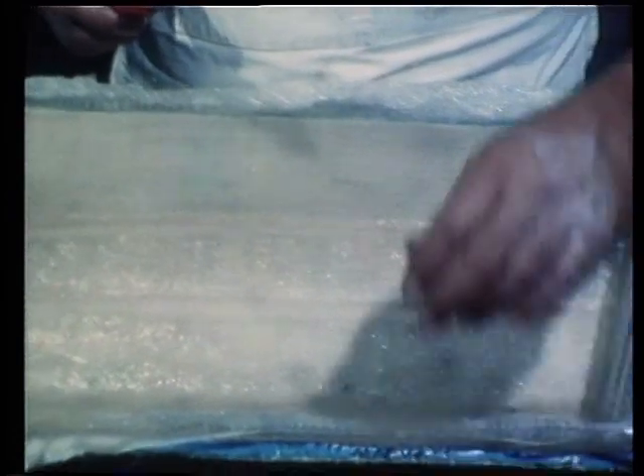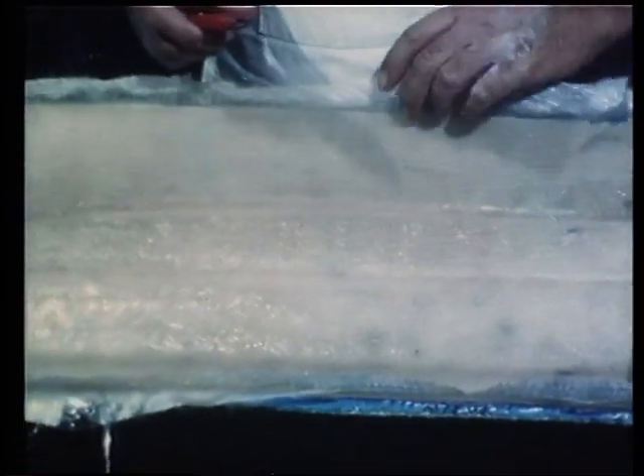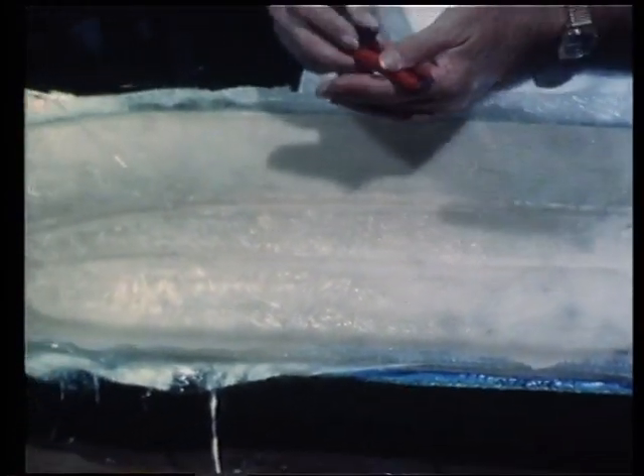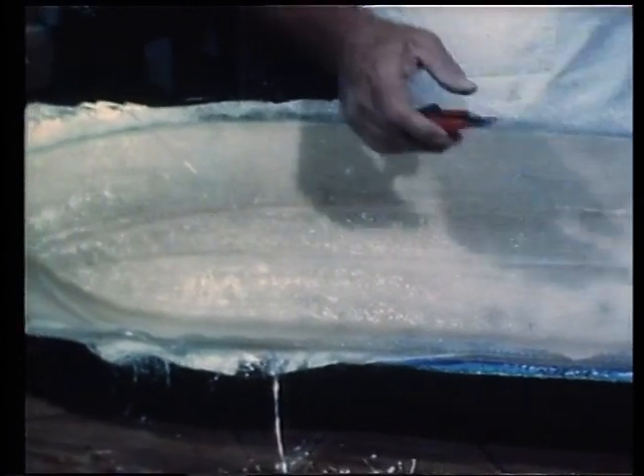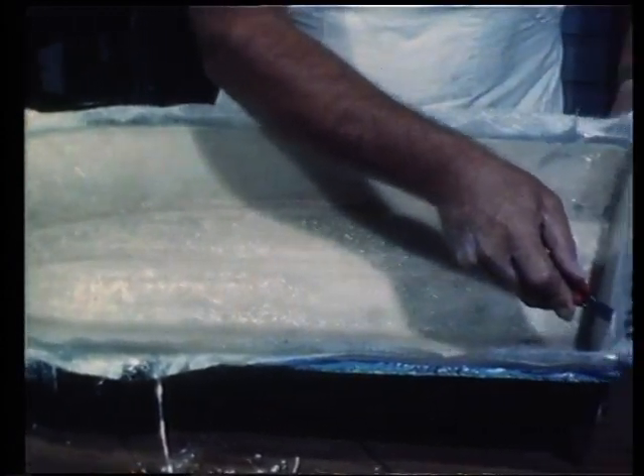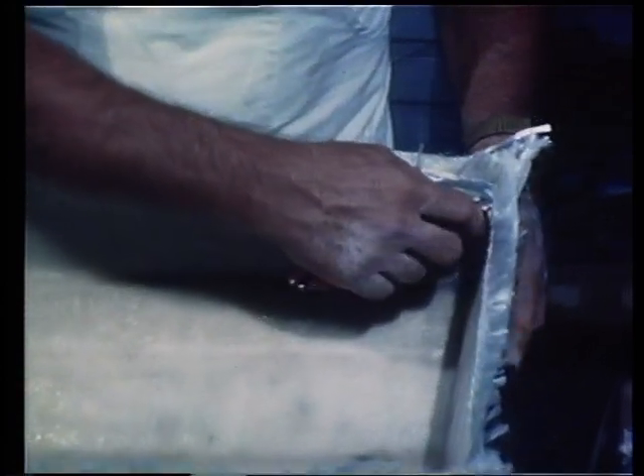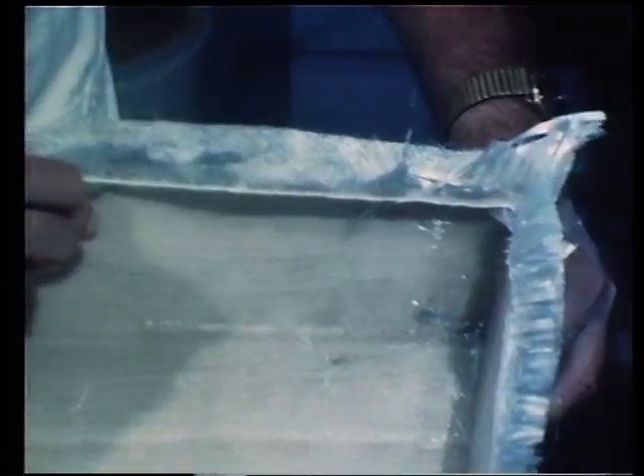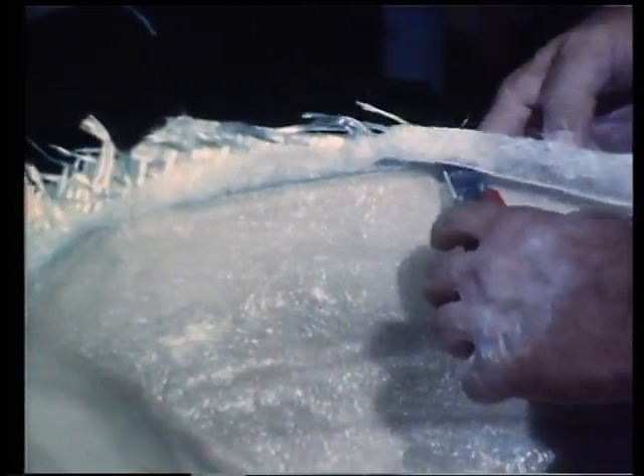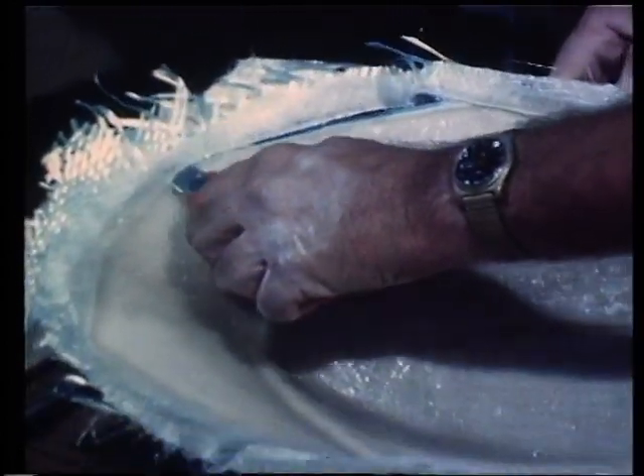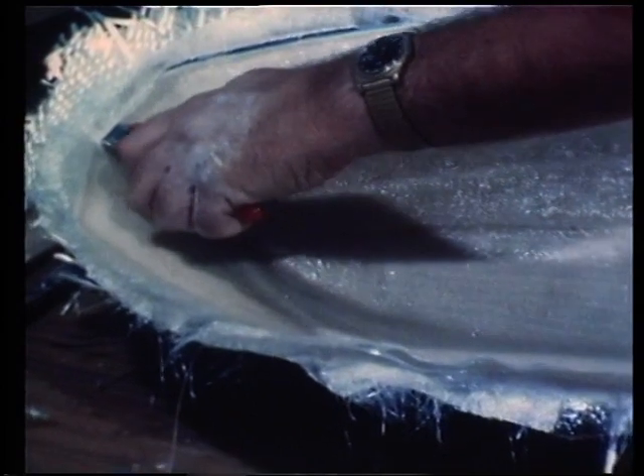And now around about an hour and a half has gone by and the curing process is well underway. In fact, the laminate has now assumed a sticky, rubbery feel, and it's now time to trim it. We use a good solid sharp trimming knife there and actually shear the laminate off against the top edge of the mould. Now, the alternative to this is to allow it to cure fully out and have to either sand it or cut it with a saw to get that flash off.